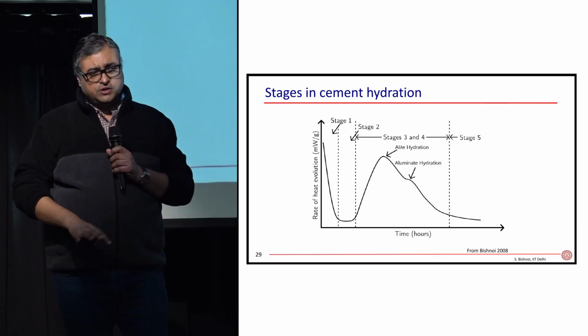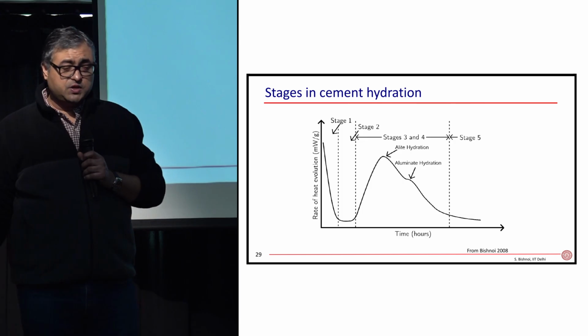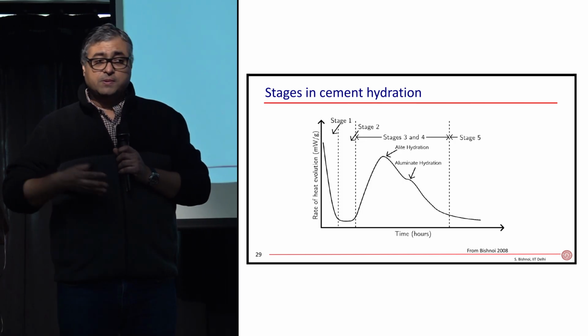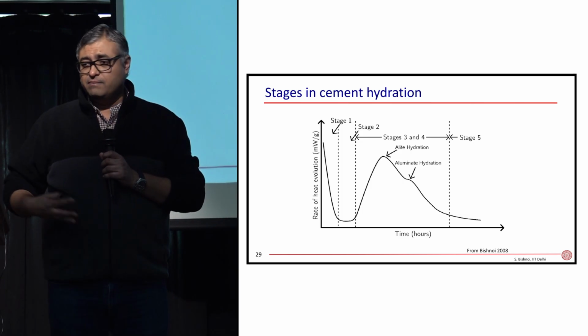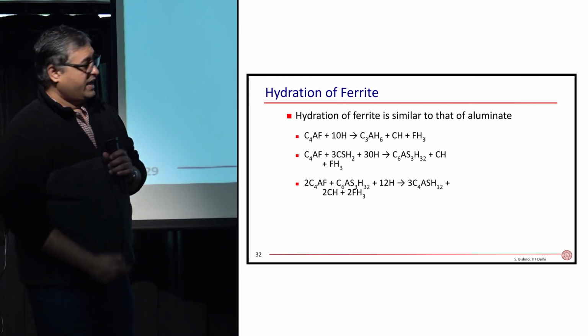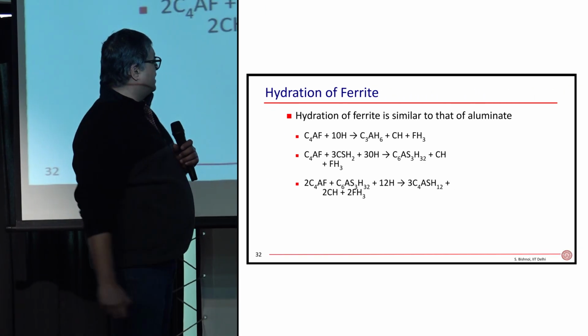And if that happens, you put the right amount of gypsum. The most common way of measuring it in cement plants used to be to optimize the one-day strength of the cement. By optimizing the one-day strength, you're able to ensure that you've put the right amount of gypsum.